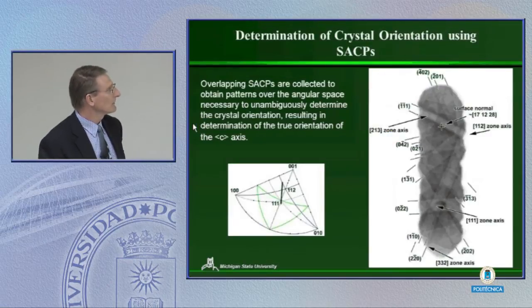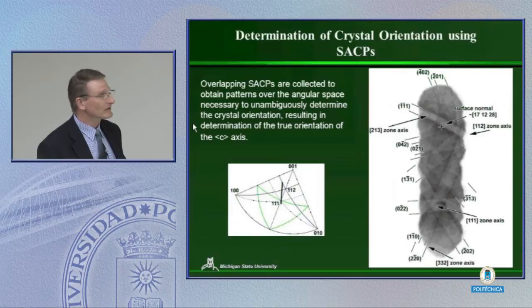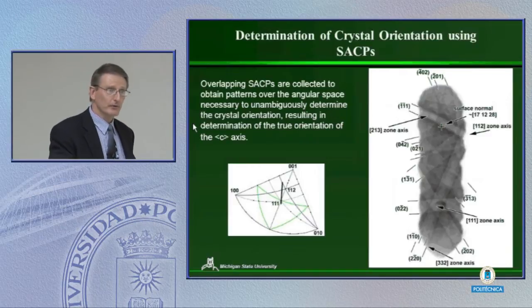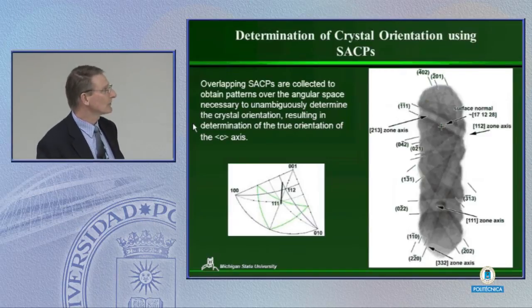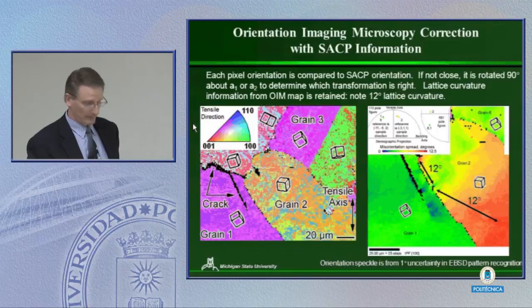And so what we found is if we use selected area channeling patterns, we can now go in there, and in particular, if we focus on this zone here, we can see in one of the three 220 bands, we can see the superlattice bands. Those superlattice bands then allow us to determine exactly where our orientation is within this stereographic quadrant.